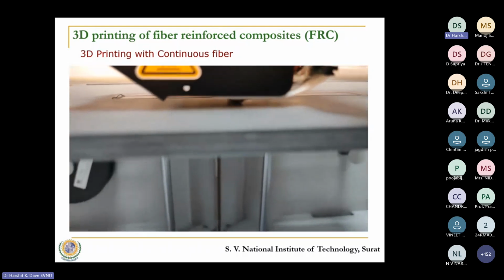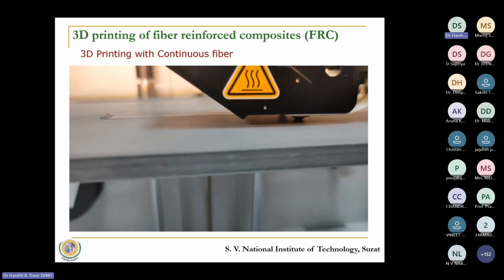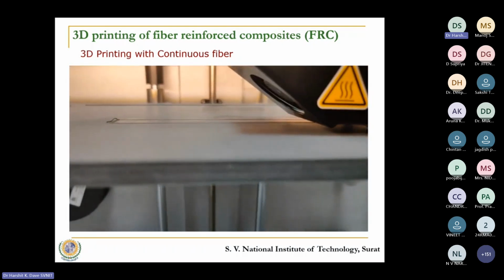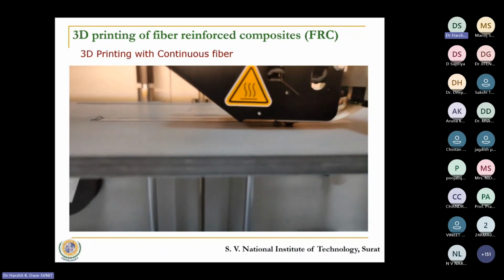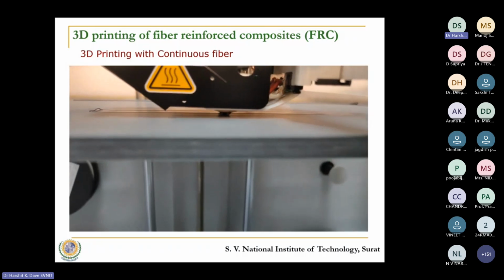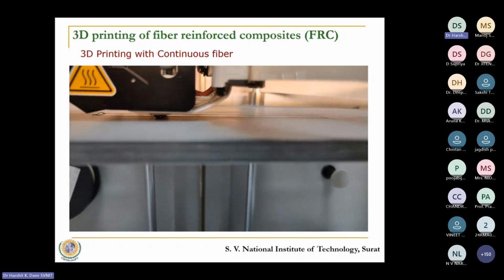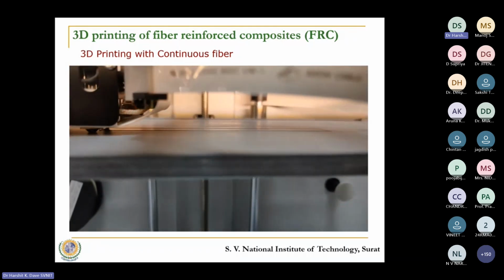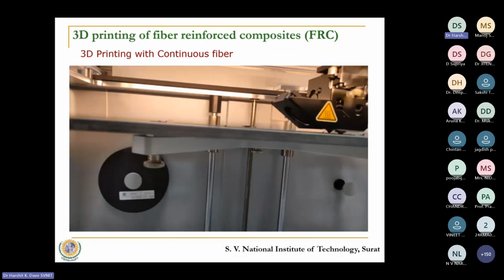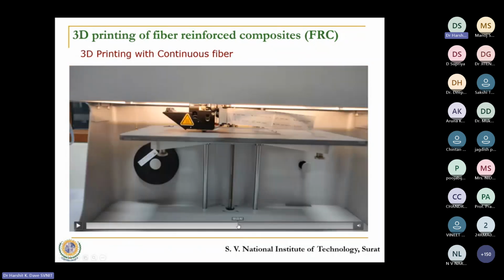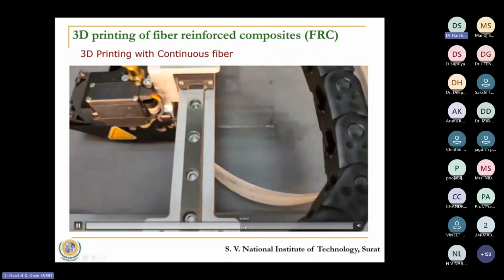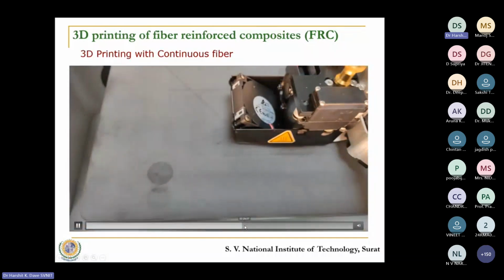Some of the first few layers are layers wherein the polymer is being deposited. Because this has the chopped carbon fiber, this polymer appears black in color. And then we are mixing glass fiber, which appears white in color, so that would be slightly easier for us to identify. So this process goes on. And there we see that in a particular layer, the glass fiber is getting deposited.